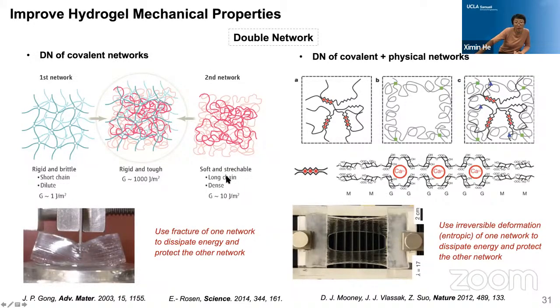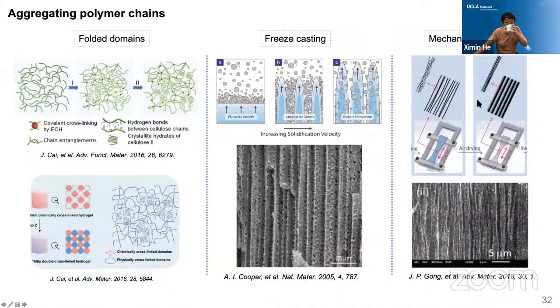Therefore, another very effective strategy was developed by Professor Jianping Gong in Japan and Professor Zhigang Suo at Harvard. So this strategy utilized a double network. By introducing the secondary network into the primary network, this network can protect the primary network by helping dissipate the energy, so that the overall toughness of this double network gel can be significantly enhanced. And then there are multiple follow-up strategies, for example, by using folded domains or freeze casting or mechanical training.